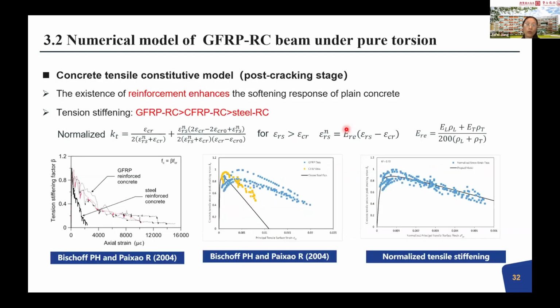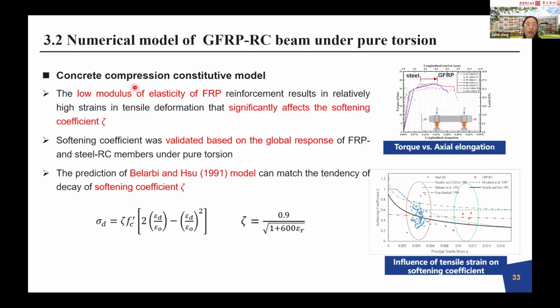And for the constitutive models, first, the tensile constitutive model, which governs the post-cracking stage. We also developed a normalized tensile stiffening coefficient for FRP and even for steel RC beams, because the longitudinal Young's modulus difference causes different tensile behavior after cracking. So we finally normalized this tensile stiffness, and we can involve both steel and FRP. And then we also introduce a more appropriate softening coefficient for FRP-RC beams.